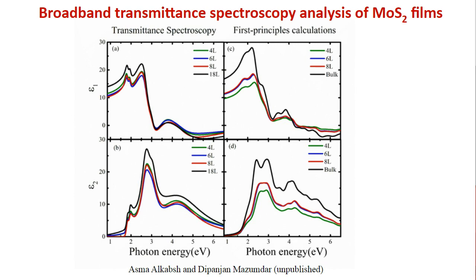And that took Asma, who is the first author of this work that will be published soon, 1 year or so to come up with a systematic process to analyze these few layer materials, right? Because we were seeing this artifact that a single layer had much higher dielectric constant than 4 layer, which means that as you reduce the material, the dielectric constant keeps on increasing. That is unphysical. That's the opposite trend we expect. And that was pretty much due to what we now know is from the substrate.